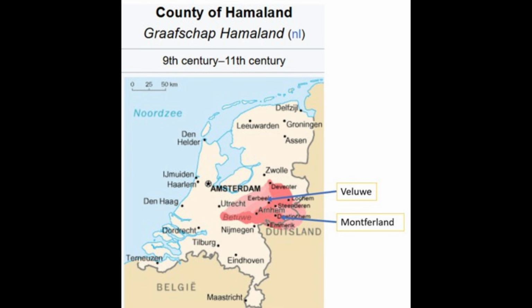The area where the sword was found in the Netherlands was historically called the Hameland and encompasses roughly the central area of the Netherlands, covering both the Veluwe and the Montferland region. In Viking times, iron was produced in the Hameland region on a mind-boggling scale. We know from slag heaps and open pit mines that in the Veluwe area more than 55 million kilograms of iron must have been produced in the early Viking times.